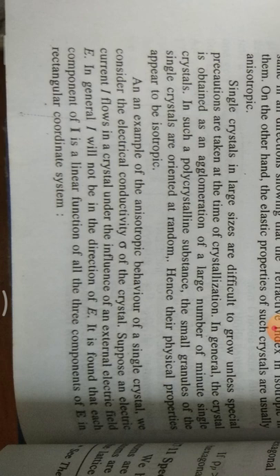In general, the crystal is obtained as an agglomeration of a large number of minute single crystals, in such a polycrystalline substance. The small granules of single crystals are oriented at random. Hence, their physical properties appear to be isotropic. As an example of the anisotropic behavior of a single crystal, we consider the electrical conductivity σ of the crystal. Suppose an electric current I flows in a crystal under the influence of an external electric field E. In general, I will not be in the direction of E. It is found that each component of I is a linear function of all three components of E in a rectangular coordinate system.